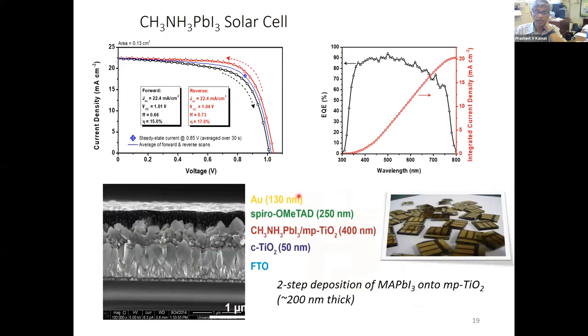Again, to show you the solar cell structure, this was done earlier. We made lots of cells, and this is your FTO on which you put compact TiO2 and then mesoscopic TiO2, the methylammonium lead iodide film, hole conductor, and the top contact. Then you characterize your cells, and we got about 17%. I think we went up to 18-19%, and then we claimed victory and moved on, because everyone was so competitive, we couldn't stand in competition in making it.